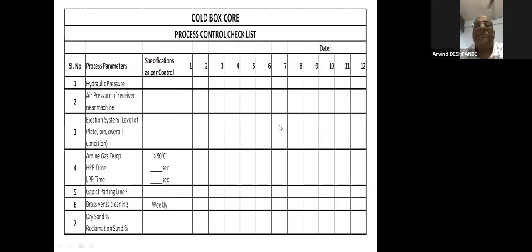I have assumed that basically the sand which we are using is okay as per the specification. My topic is how to make a process control checklist. Now I'll start. First will be the hydraulic pressure specification as per control plan. Hydraulic pressure, then air pressure, both are important. Hydraulic pressure is for the clamping of the core boxes, with no gap at the parting line. Sufficient pressure should be there so that while shooting, the core box stays in the same place. There should not be any gap. Otherwise, across-parting dimensions of the core will increase, sand spillage will occur and the core will not be dense.